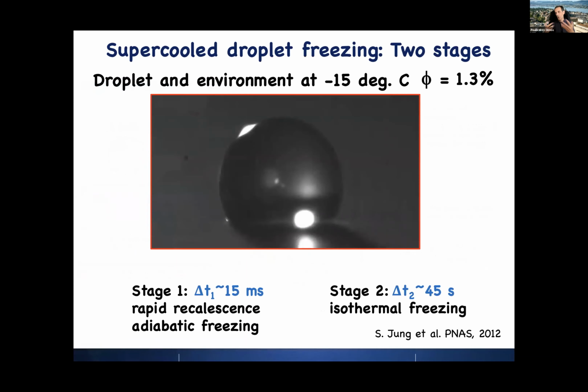So I will show you the result of a process like this in the next slide, where I have a droplet on the surface. We didn't do much architecturing on this surface. It is a hydrophobic surface, I think. And now we have an environment where everything is at a low temperature, minus 15 degrees. And as you see here, the droplet is still in a liquid state. And then we're waiting and waiting, despite the minus 15 degrees. And then we observe the following.